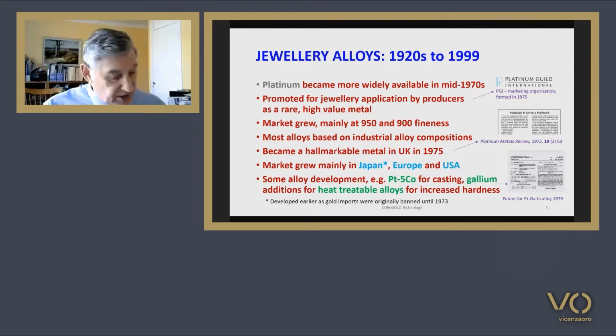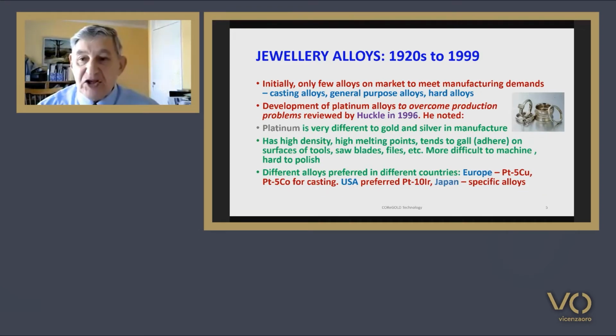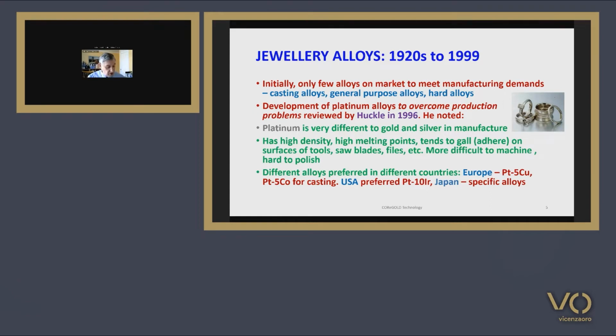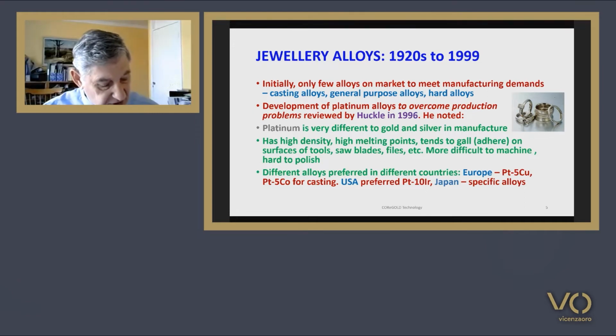Initially, only a few alloys were on the market to meet manufacturing demands, and these were classified as casting alloys, general purpose alloys, and hard alloys. Huckle of Johnson Matthey reported on the development of platinum alloys to overcome production problems at the 1996 Santa Fe Symposium. He noted that platinum and its alloys had some different characteristics compared to gold and silver, notably its weight, hardness, and thermal conductivity, and that its alloys have a high density as well as very high melting points. Its high surface resistance leads to clogging or galling and high wear of saw blades, files, and machine tools.